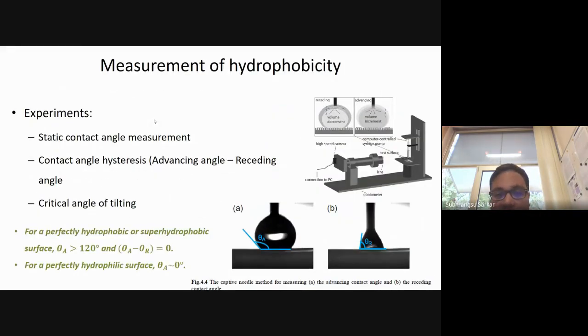Before we go into the details of the experiment, I would like to quickly say how we measure hydrophobicity. There we put a sample in one of these parts of a setup, and then we use a syringe pump. A syringe pump is used to control the flow of water extremely accurately on the surface. Not flow, but the drop of water. Let's say if I want to drop 50 microliter of water, it will be 50 microliter, it will not be 100 microliter or 20 microliter. And then there is a camera which is facing perpendicular to the interaction space between the water and the sample in question. And that camera is connected to a computer.